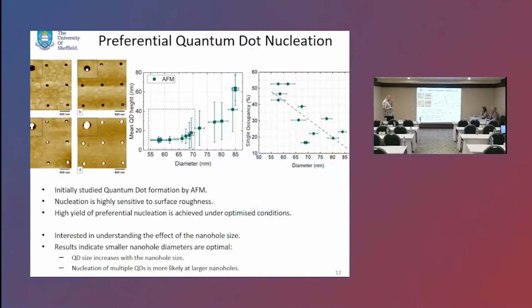Now the dots may be poking slightly below and you can't see them because of the contrast, but you can then see that we're definitely getting dots in all the pits, but occasionally we're getting larger objects, and then as we go even further you end up with quite big and probably dislocated dots. So we're looking at the effect of the diameter on the quantum dot height. Are we actually controlling the dot growth in some way?